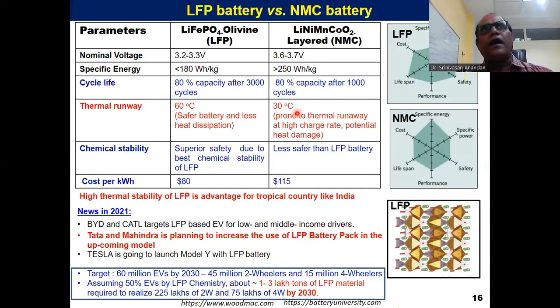So when there is a high temperature in the surroundings, obviously the temperature inside the battery increases, and a lot of highly flammable liquids are there inside the lithium-ion cell. For example, the electrolyte and carbonate solvents are highly flammable. Whenever there is a temperature increase in the lithium-ion battery, first it damages the separator, and subsequently the electrolyte also gets decomposed, and a lot of exothermic reactions happen, and the temperature keeps building inside the lithium-ion cell. Finally the explosion takes place.